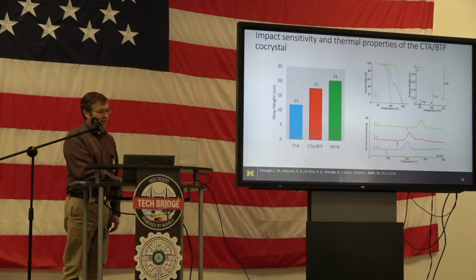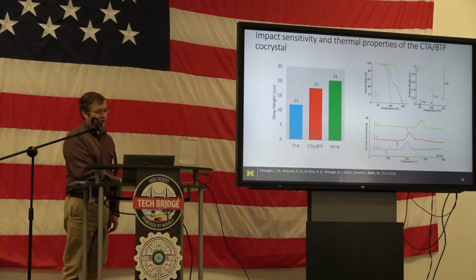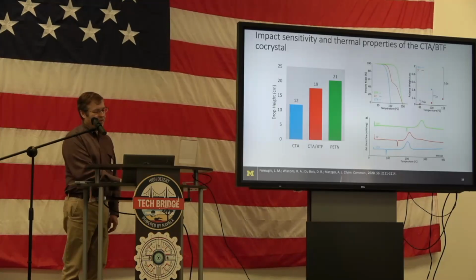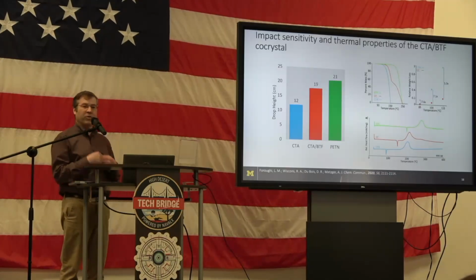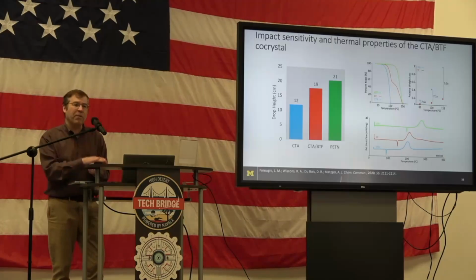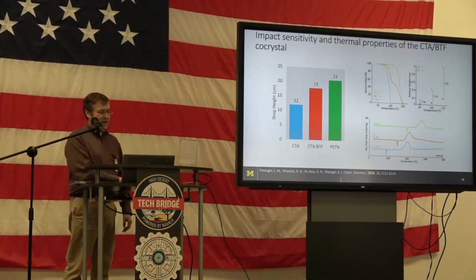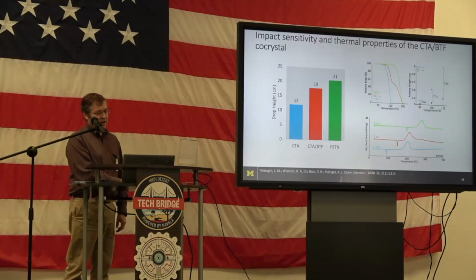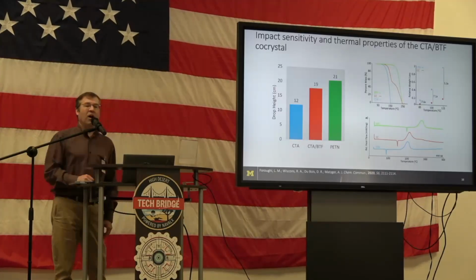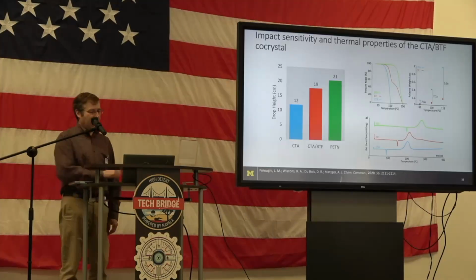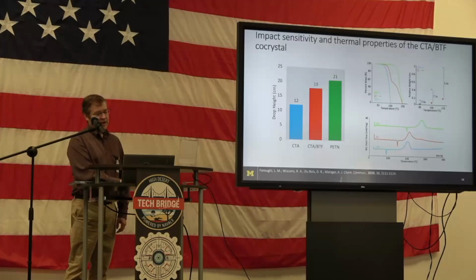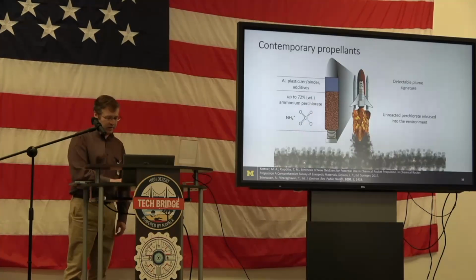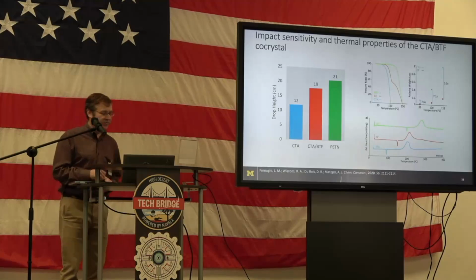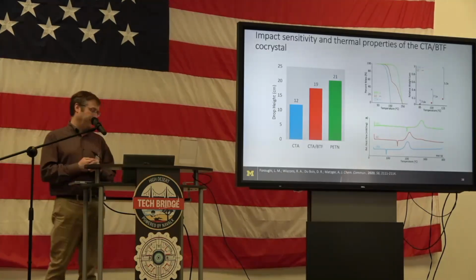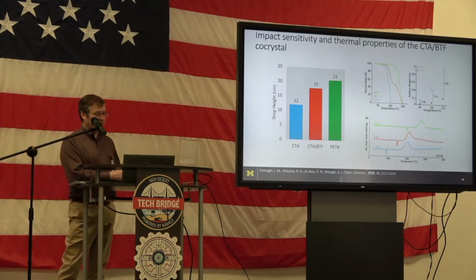So we looked at the thermogravimetric analysis, and you can see that CTA sublimes very easily. We get a little bit less of that in the co-crystal. So the co-crystal is more stable, so it suppresses the vapor pressure of the CTA. And in fact, we can look at that quantitatively, and you can see at different temperatures, this is the suppression of the CTA vapor pressure that you get at each of those temperatures. So at 85 degrees, you're already down at about a 7.5 decrease, times less volatile. Also, it changes the thermal properties. So here's the DSC.